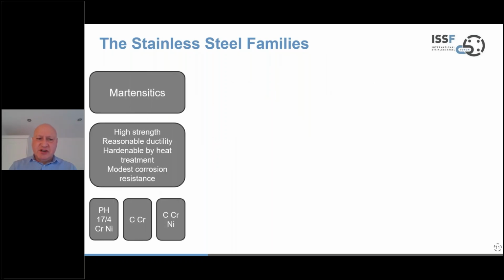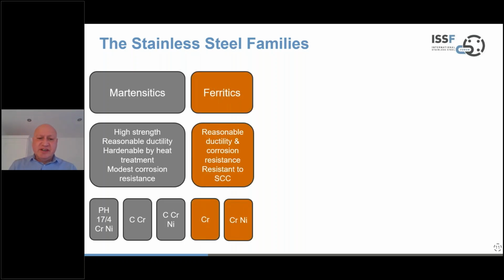So let's look now at the stainless steel families, just to try and put things in context. So very early stainless steels that were produced almost 100 years ago are in the martensitic family group, and they have high strength, reasonable ductility, but only modest corrosion resistance. And these are the chromium carbon steels or the chromium carbon nickel steels, or include, some would argue, the precipitation hardening group. You then have the ferritic family of steels, which are straight chromium or chromium nickel steels, slightly better corrosion resistance, and they are resistant to what is known as stress corrosion cracking, which is particularly important.